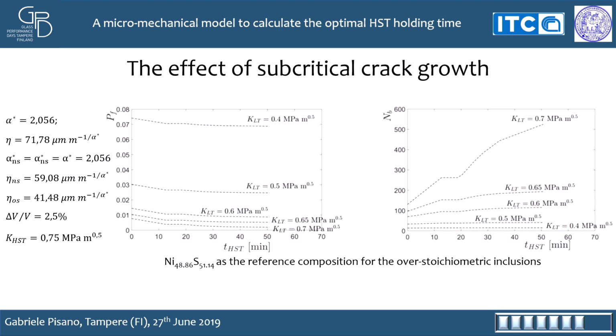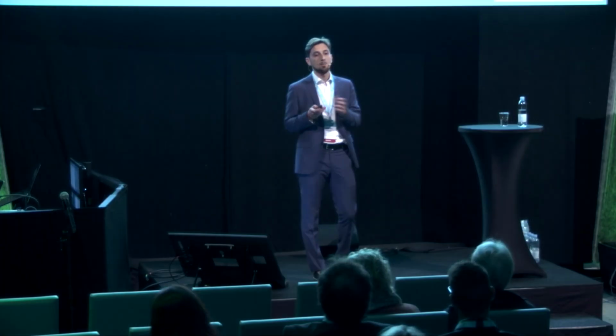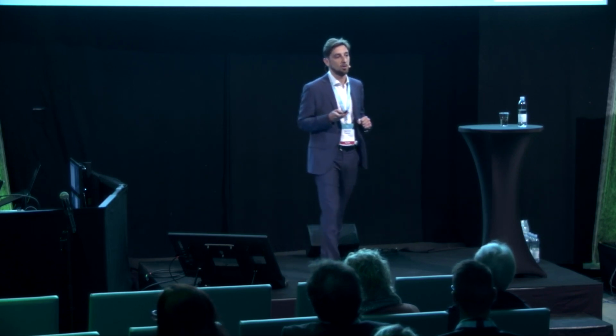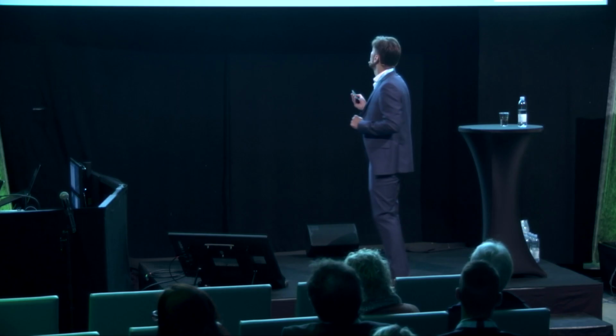This is why we think that the most reliable value for the stress intensity factor to be considered critical for having breakage in the long term is between 0.6 and 0.7. This must not be striking, as it is close to the fracture toughness for glass, that is 0.75, because this is subcritical crack growth for interior cracks, not for surface cracks, in which water is not present, and so we can expect that the subcritical crack growth is much more limited than for surface cracks.